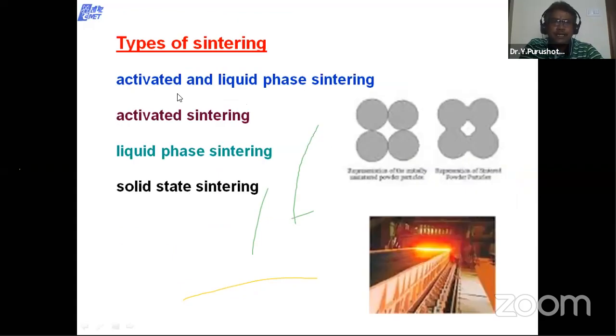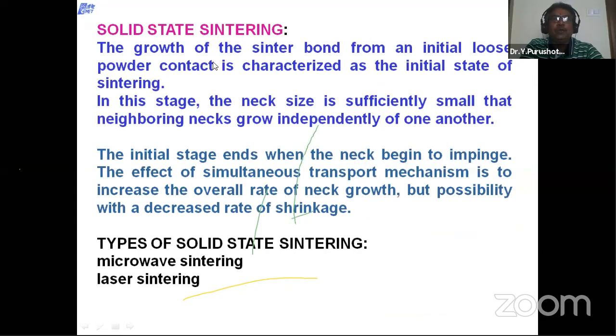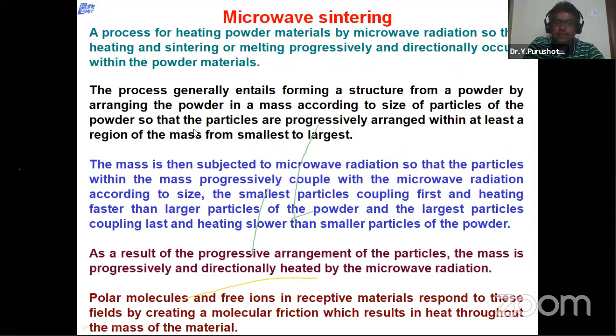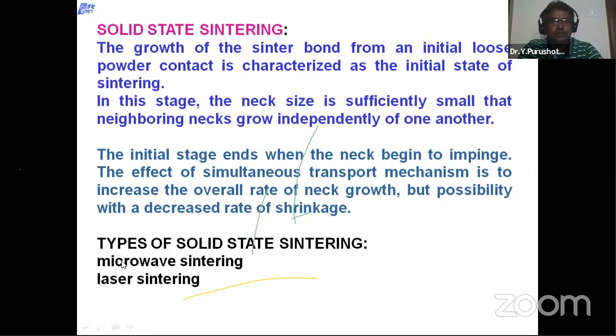And now the types of sintering: activated sintering, liquid phase sintering, and solid state sintering. In solid state sintering, the growth of the neck from an initial loose powder compact is characterized as the initial state of sintering. In this stage, the neck size is sufficiently small that neighboring necks grow independently of one another. And there are two types: microwave sintering and laser sintering.